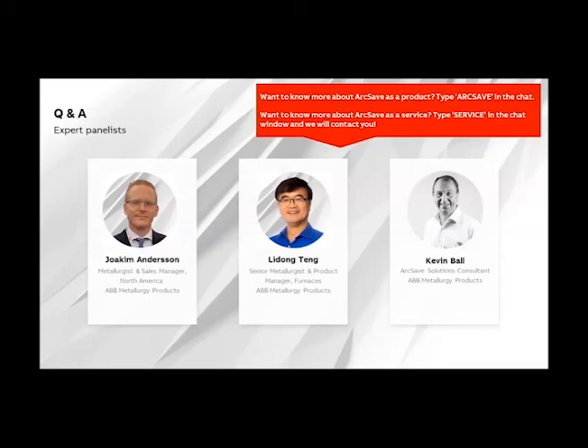Thanks, Kevin. I have a question for Joakim. Do you have any references relating to revamp projects for installing a stirrer on an existing electric arc furnace? Yes, a good question. If we look at our reference base regarding ArcSave, 4 of our installations are from a revamp. So we have Avesta Outokumpu, which was certainly a revamp project. We have SDI, Steel Dynamics in Roanoke. We have POSCO Puyang, and we have CEA. So it's fully possible to do a brownfield revamp. Of course, what you need to think about is that you probably need a new lower shell or a stainless cutout in the bottom of the furnace.